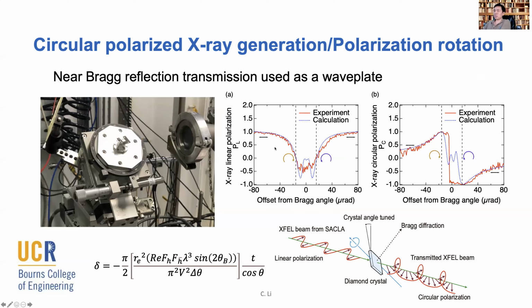So what I'm showing here is our measured linear part of the polarization and circular part of the polarization across different offsets of this diamond plate through a Bragg angle. This is plotted versus our own calculation based on what people know about these X-rays. I think the tricky part comes from the fact that meV bandwidth X-ray beams are much more difficult to deal with. Maybe there's just a larger angular divergence, or maybe that has something to do with the bandwidth itself.